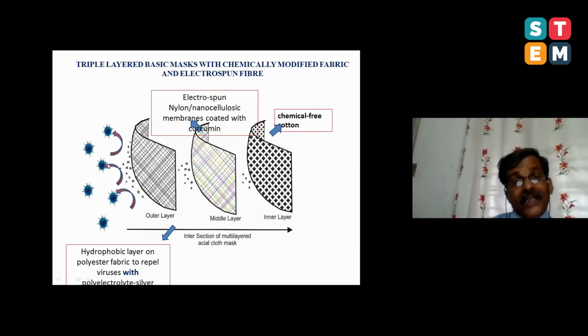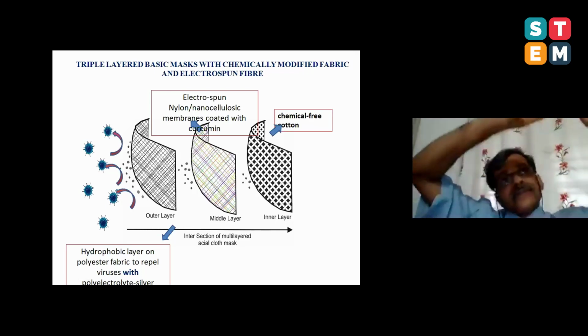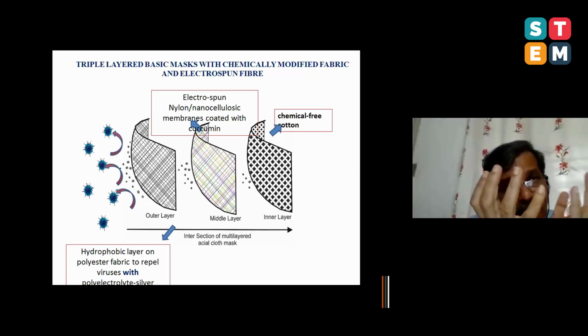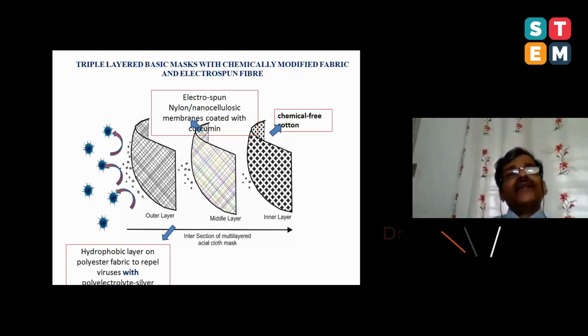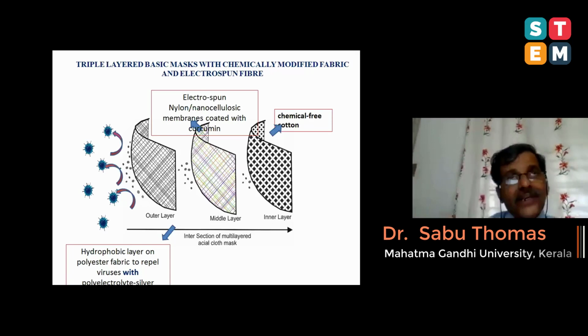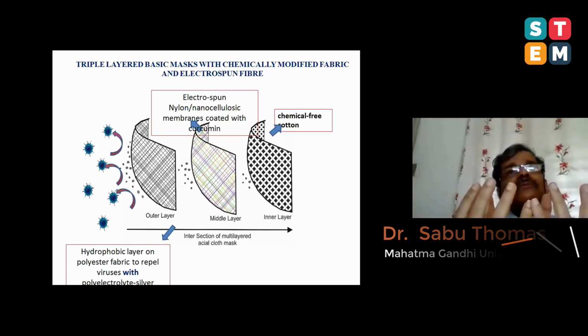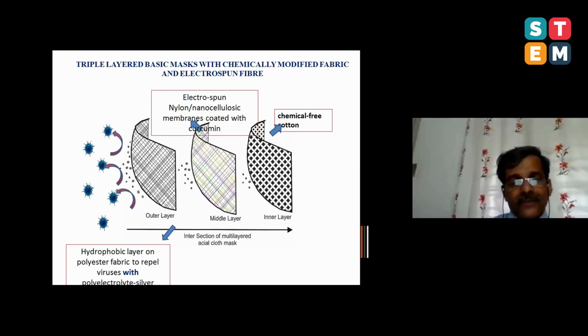If at all some coronavirus is getting into this middle layer, nanocellulose can kill them because nanocellulose has a positive charge and coronavirus has a lipid layer which is negatively charged. So there could be electrostatic interaction. And because of the electrostatic interaction, the outer layer of this coronavirus will be destroyed. So this is our new protocol we have given for the Indo-US project.